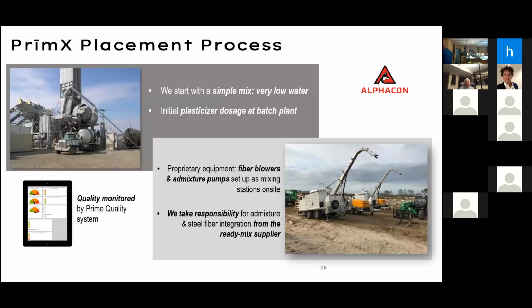How do you make that concrete? Well, first of all, there needs to be a due diligence process ahead of any kind of operation. Essentially that means sampling sand and aggregates, and completely qualifying cement from the paperwork that comes from the cement plant. You're going to look at the fineness blend. You're going to look at the different mineral phases that are present in your Portland cement, which we use type 1 and type 2, but that doesn't mean that cement is everywhere the same. It doesn't have the same reactivity. It doesn't have sometimes exactly the same exothermic reactions upon hydration. So all that is completely qualified, including by pouring beams per ASTM to qualify and quantify shrinkage, not only in its amount, but also for the way shrinkage occurs within a timeline. There are ASTM protocols for this, and that's part of it even before the placement.